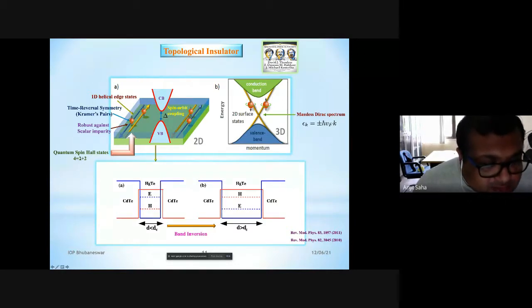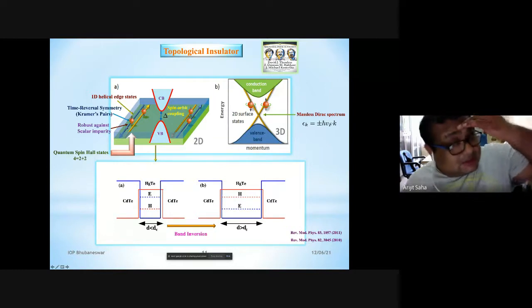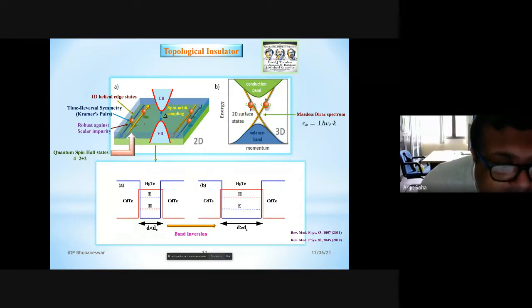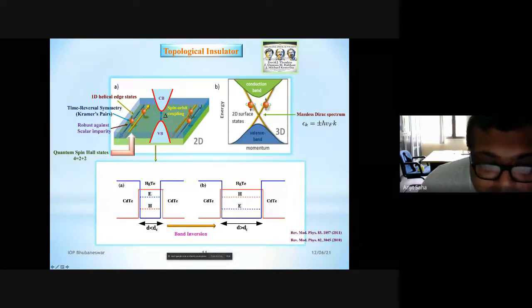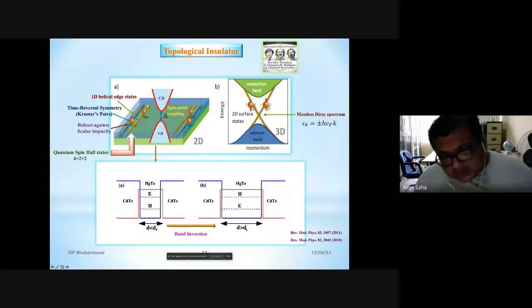So that means it's 2 copies of the quantum Hall. So you have 2 plus 2 at the two edges. And also these modes, again, are robust against impurity. And why? If you put an impurity here, and if you want to allow backscattering, so the right moving can become left moving due to backscattering, but you not only change your direction of motion of the electron, you have to reverse the spin also, which is not possible for a non-magnetic or scalar impurity. So this is robust against scalar impurity or non-magnetic impurity. Obviously, if you put a magnetic impurity, then immediately time reversal symmetry will be broken, and you will start getting backscattering.